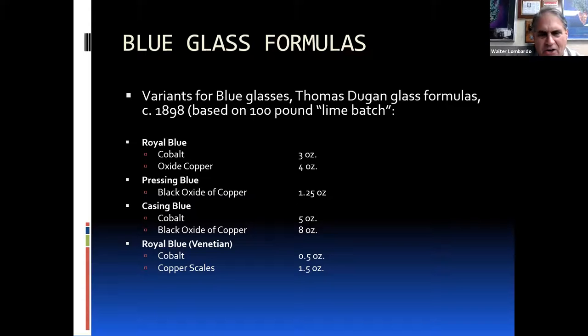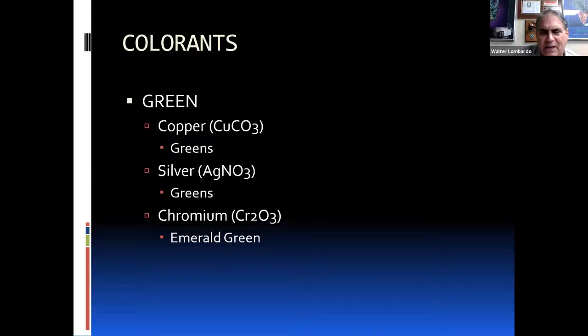Casing blue, which is a little bit darker, has a little bit of cobalt as well as copper oxide, in fact, that's a dark one. And then a different type of royal blue, which they call Venetian, was basically cobalt and what they call copper scales, which I believe was a copper sulfide. And again, very small amounts to get that. So you can see that you don't need a lot of the coloring agent to create these rich colors in the glass. Same thing in minerals and gemstones. A fraction of a percent is more than adequate color.